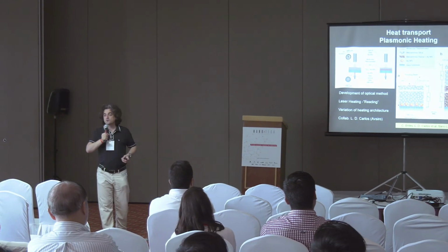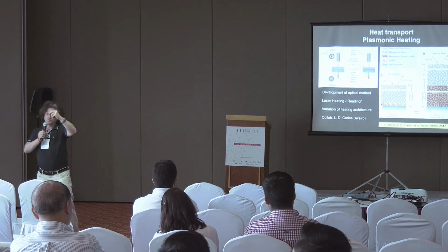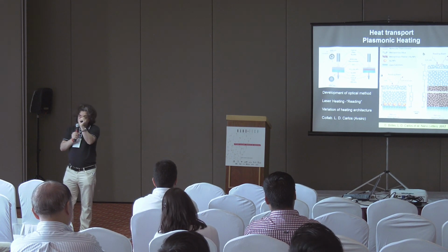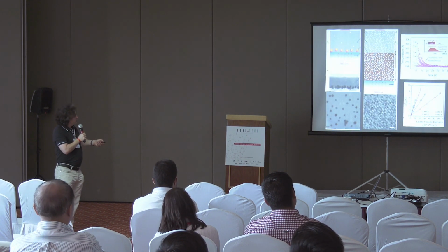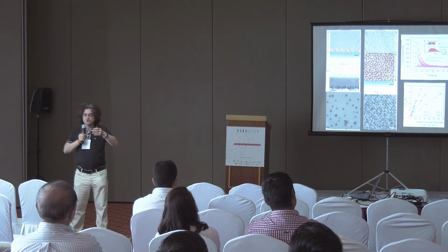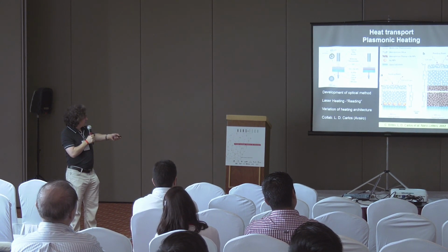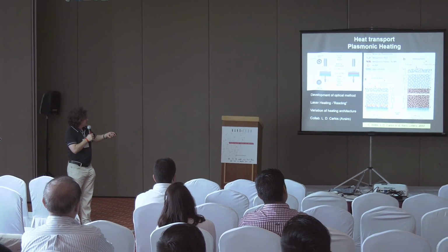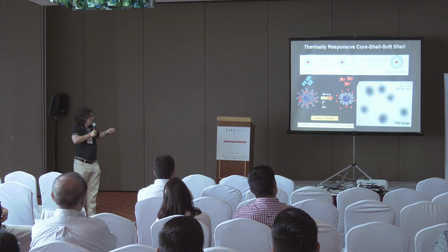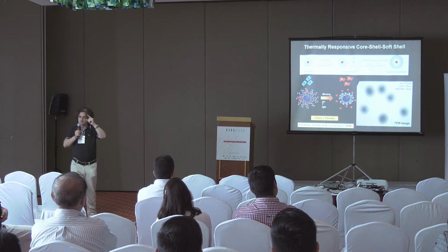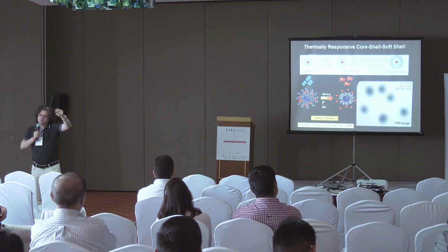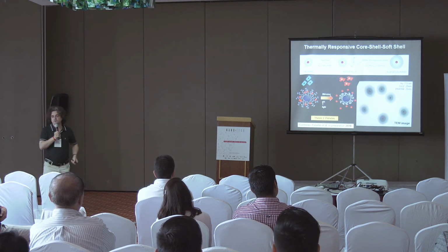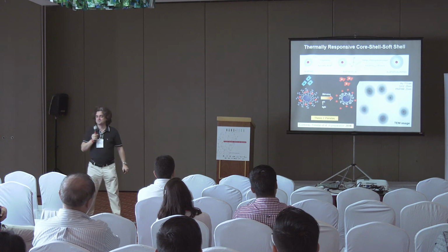And then here, at a given distance, which is tailored by the film thickness, we deposited, this we did with Luis D. Carlos in Aveiro, a molecular thermometer. It's a molecule in which the emission is very finely dependent on the temperature. So by working in dynamic systems, we could have a good idea of what the thermal properties of this material were. And then we adapted this thickness. The laws are not exactly the same, in order to optimize the shell here, in order to let the heat flow from here to here. Yeah. It's a long work.